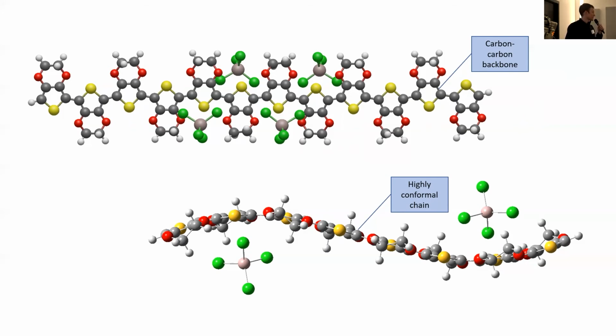However, one of the first things that I discovered was that these anions have a real strong energy well effect in these locations along the polymer backbone. Obviously not what you want in a battery cathode. When you're trying to put a charge carrier through the bulk of an electrode, what you're looking for is a really nice flat profile of energies of all the locations of the anion as they make their way through the electrode. This highly localized energy system then creates high levels of hysteresis and quite a bad energy efficiency, which is seen when you actually try and produce this as a battery.